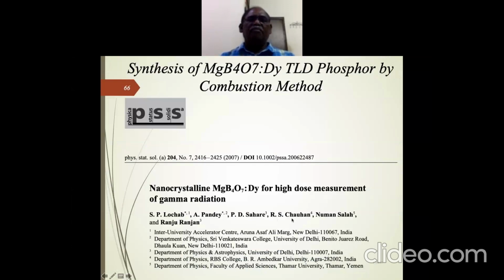Then we also have synthesized this magnesium borate doped with dysprosium. This material is of very great interest to us because this is what is called a tissue equivalent material. Lithium fluoride and this borate, and beryllium oxide, are the only few materials which are tissue equivalent, so the energy response is very flat. Also the Z effective is approximately equal to that of tissues, and therefore the damage caused to your body is similar, or the interaction is of a similar kind, and therefore this could be used in a mixed field of radiation.